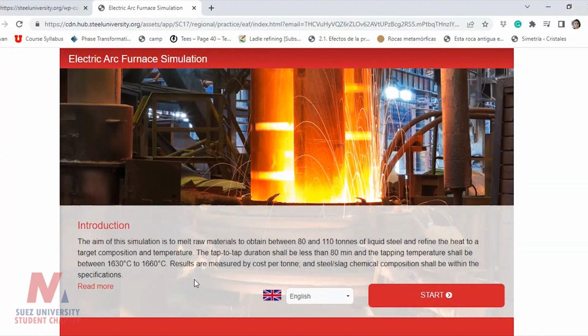You have to produce a heat between 80 and 110 tons of liquid steel to refine in the next stage. The tap to tap time should be less than 80 minutes, and the tapping temperature should be between 1630 Celsius degrees and 1660 Celsius degrees. The results, as I told you, have to be measured by the cost per ton, the steel and slag chemical composition, and the time, you just have 80 minutes.